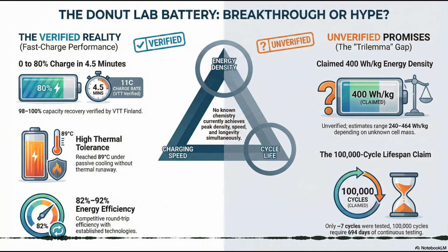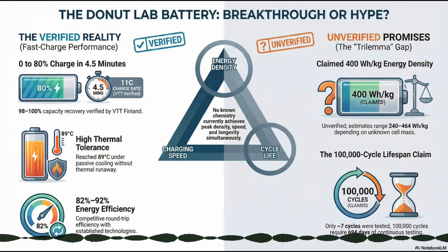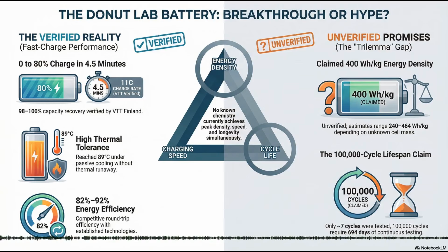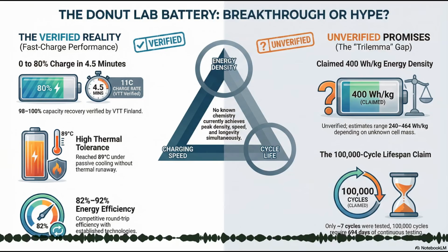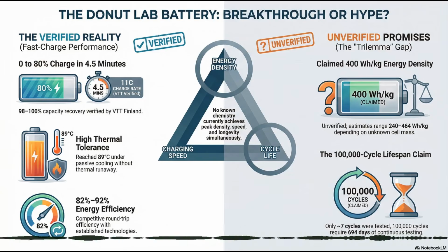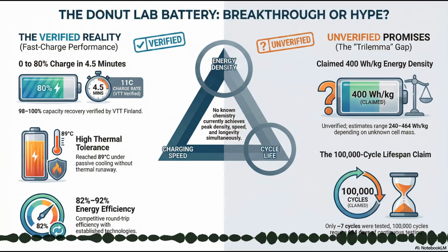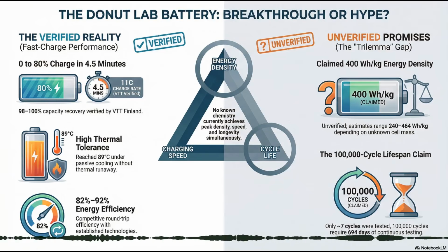But the density. That is the conflict. Typically, nanostructures have terrible tap density. They are fluffy. To get a total cell energy density of 400 Wh/kg with a fluffy TiO2 anode, the cathode would have to be spectacularly, unbelievably energy dense, or the electrolyte layer would have to be microscopically thin. This is the biggest technical mystery of the whole report. The cycle life claims and the energy density claims seem to fight each other based on known physics.